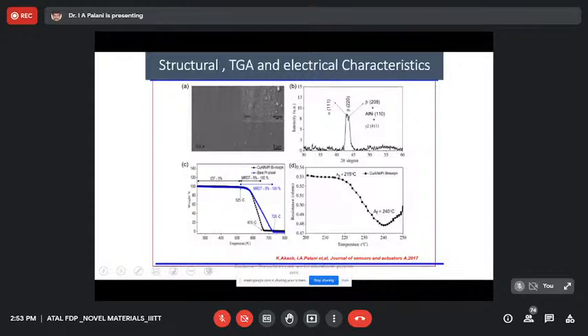Now, these are some of the characterizations we have done. One is with respect to surface morphology, where we could see the surface behavior. This is with respect to an XRD analysis, where we could get clarity about the beta phase and the alpha phase of the shape memory alloy. Here we are trying to fabricate a shape memory alloy from the pellet to the final deposition. Obviously there will be some secondary phases, but the influence of the secondary phases needs to be looked into in an appropriate manner.